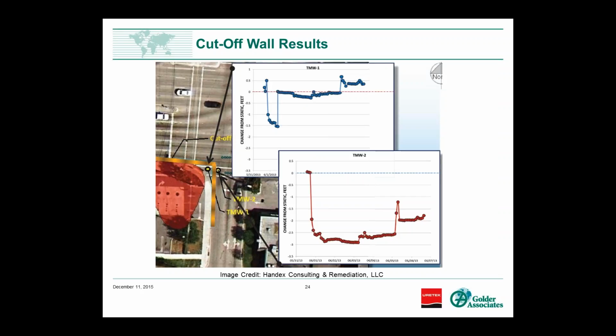Hopefully you can see these graphs okay. They only needed to dewater for about 7 days, so I think these time series graphs show pretty much the whole duration of the dewatering. The monitoring well on the left is the one behind the cutoff wall, on the contaminant side, and the one on the right is on the dewatering side. You can see that they achieved really good results with the cutoff wall. The change in static water table really stayed right at 0. There was no drawdown on the contaminant side of the cutoff wall.